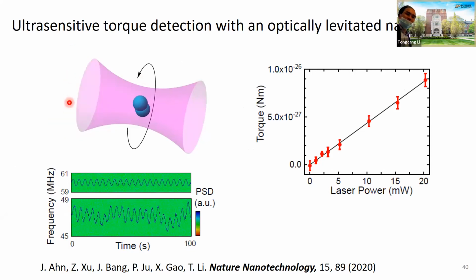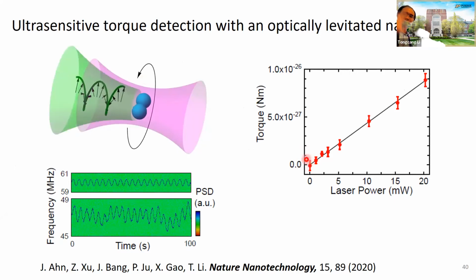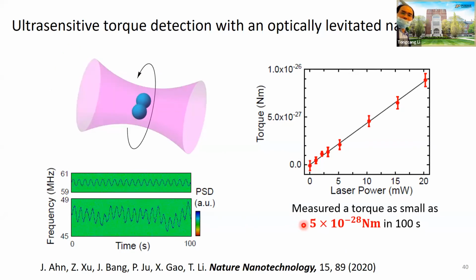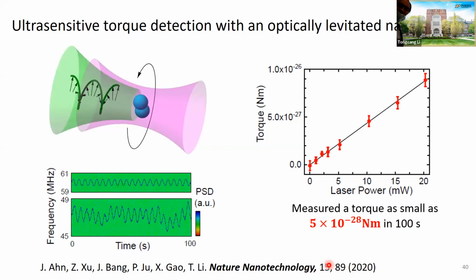When we modulate the power of the laser sinusoidally, the rotation speed will also change as a function of time. And with that, by taking data for 100 seconds, we can measure torque as small as 5 times 10 to the minus 28 newton meter in 100 seconds. So this is the most sensitive torque detector right now. I published it in Nature Nanotechnology about 2 years ago. So that's for levitated optomechanics.